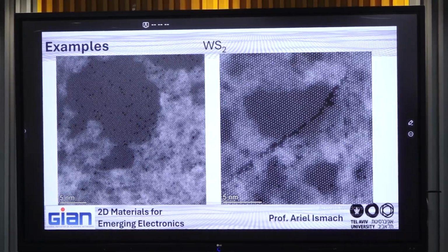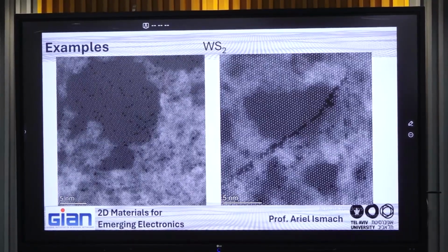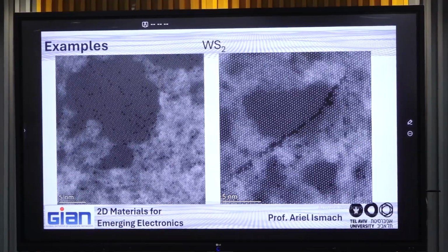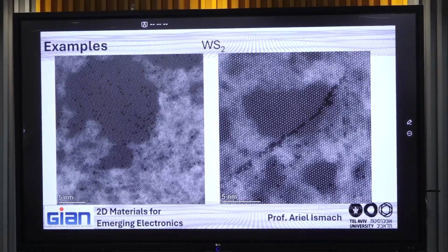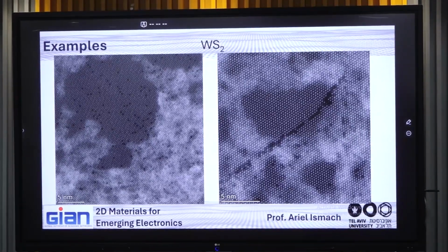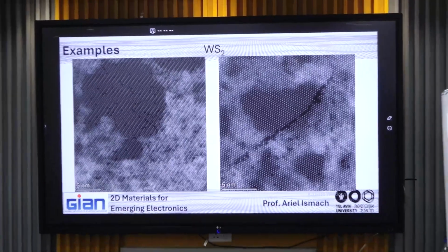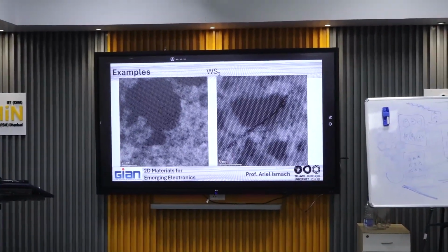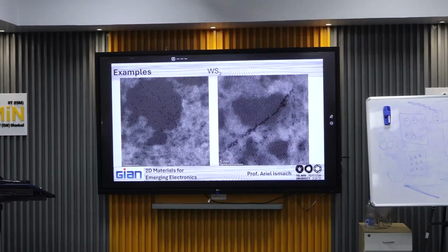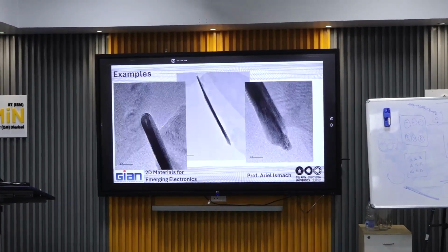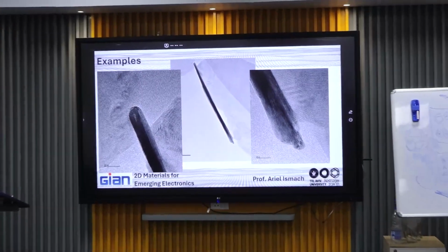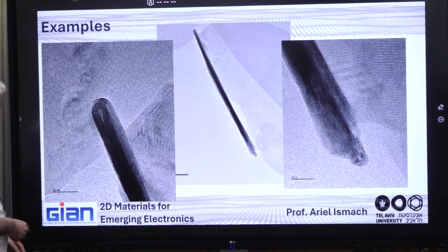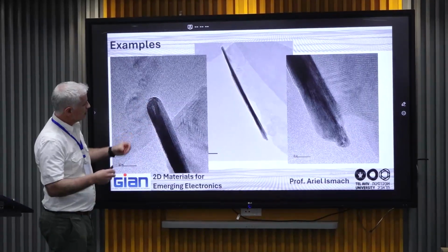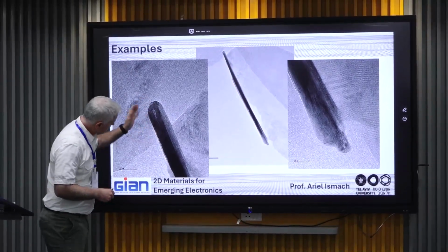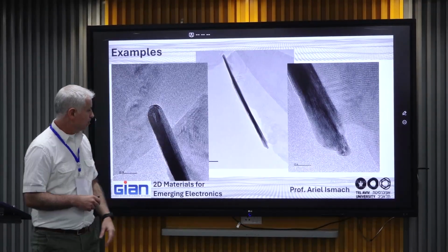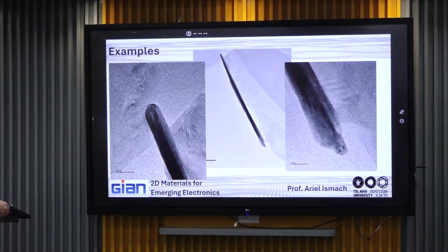People studied the defect formation and then manipulated all kinds of defects, and also saw the healing of the defect. You can see the defect moving all along. People have shown that, have published that. We didn't publish. We just were analyzing our samples. And you don't see the images here, but these are TMDs that are folded into nanostructures, and you can see the bend. Okay, on this screen you cannot see many details, but anyway,